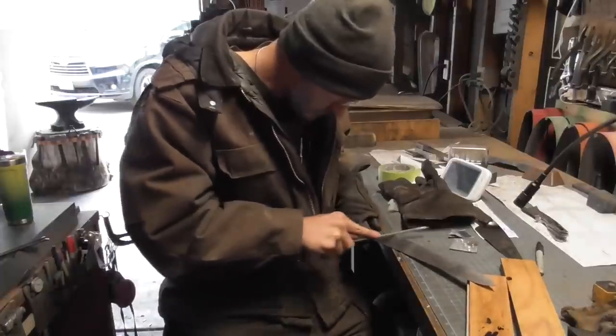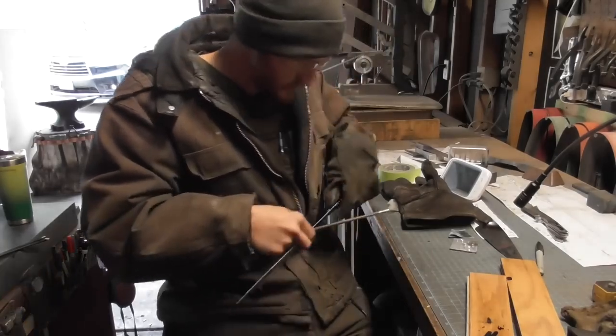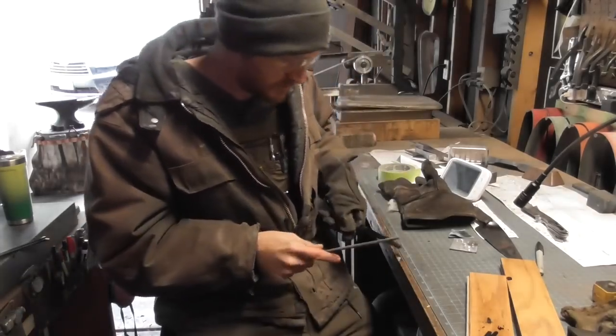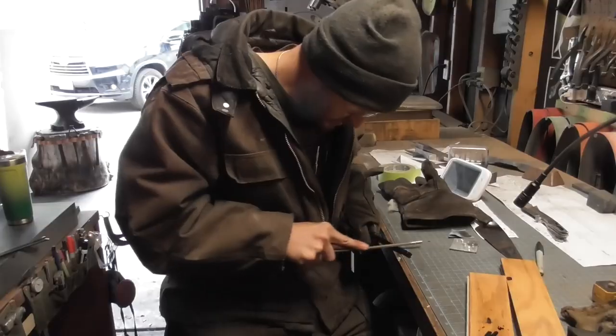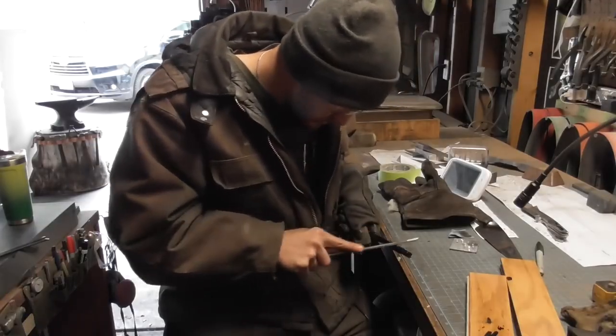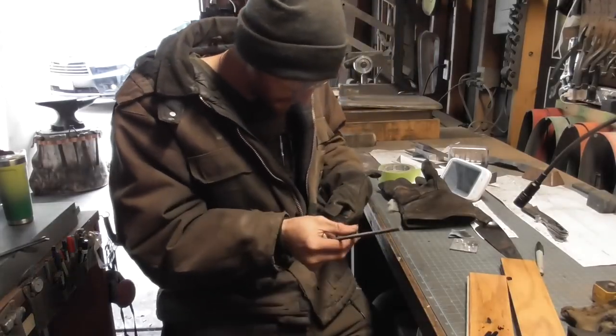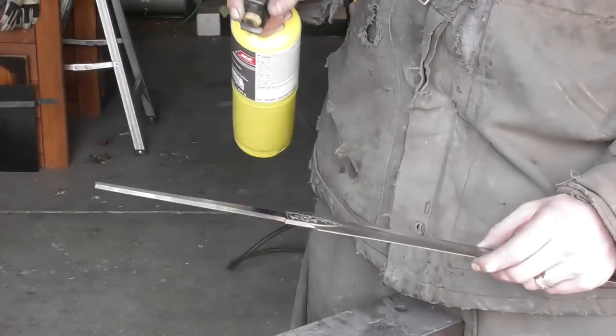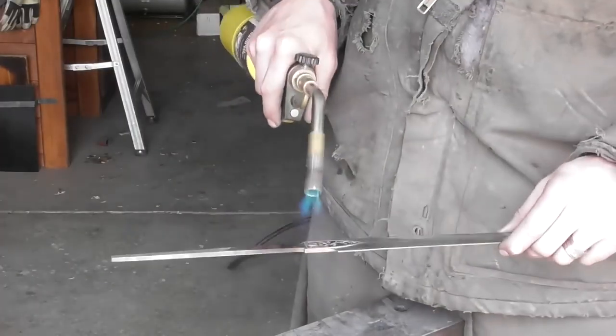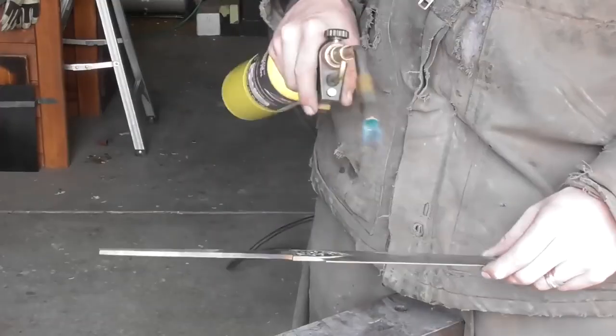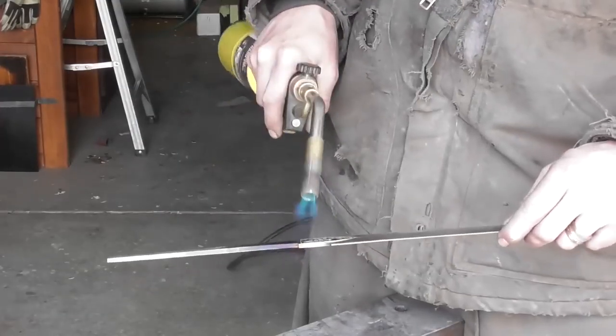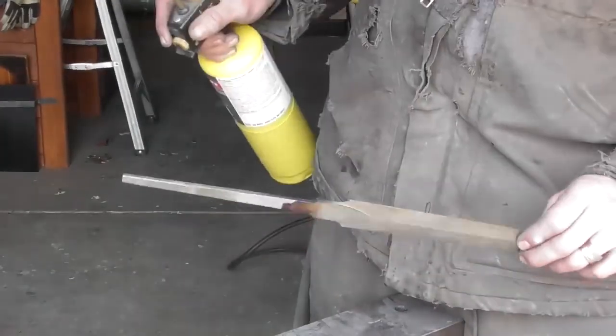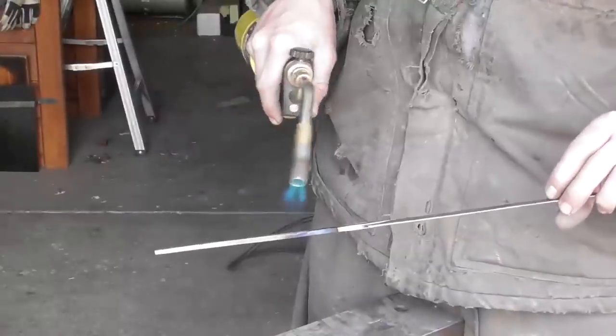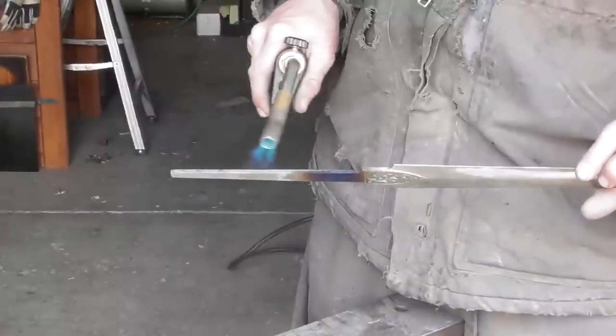But the hardened steel, you'll notice that when you file it, the file will skate across the top, versus if you file mild steel or something like I am on the tang, then it'll really bite and dig into the metal. Once the blade has been successfully hardened and tempered, then it's time to spring temper the ricasso area, especially right up where the tang meets the ricasso or meets the blade.